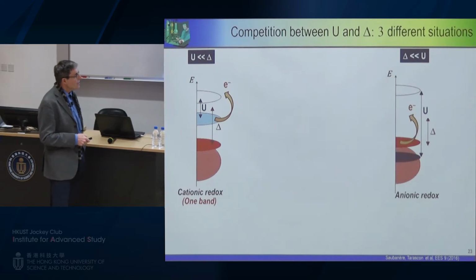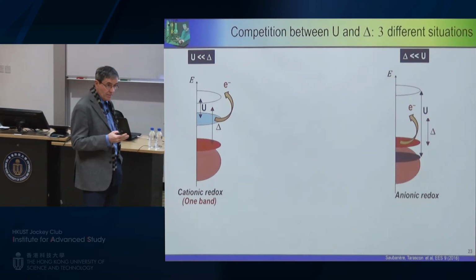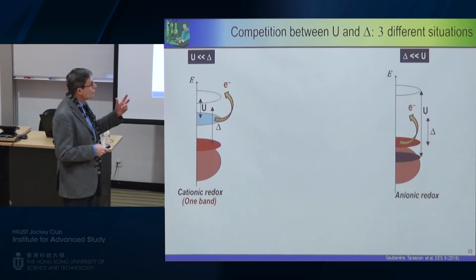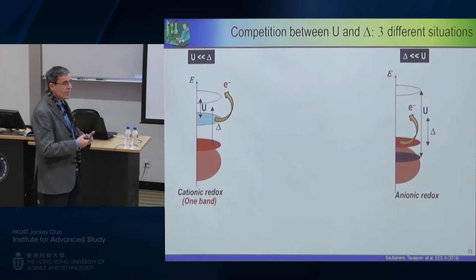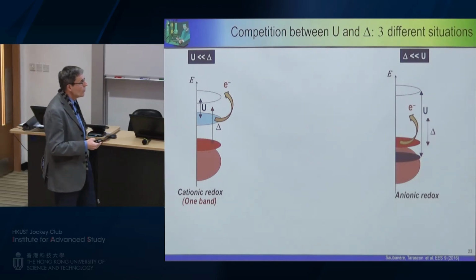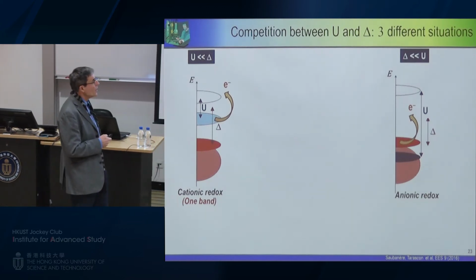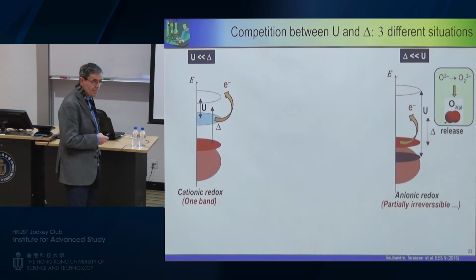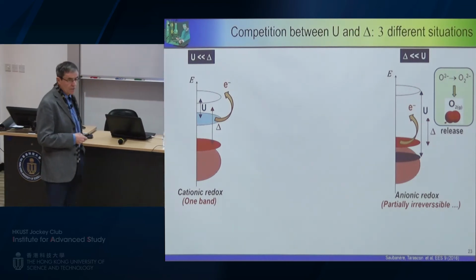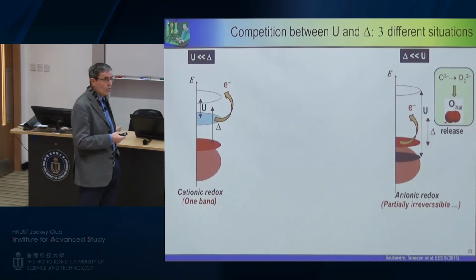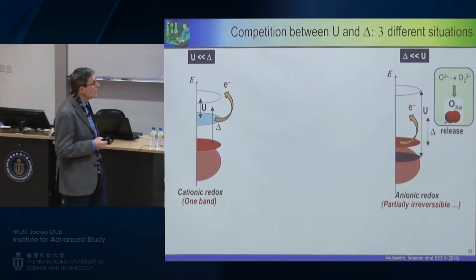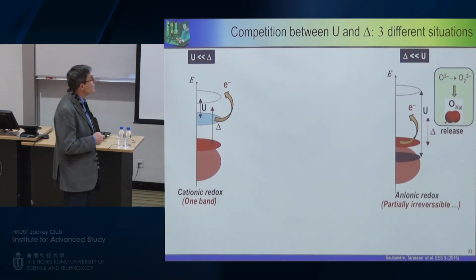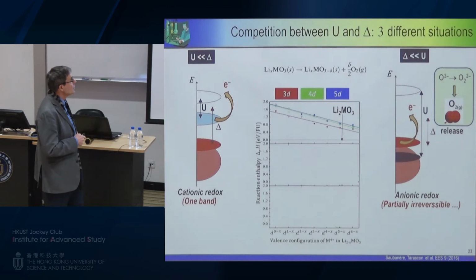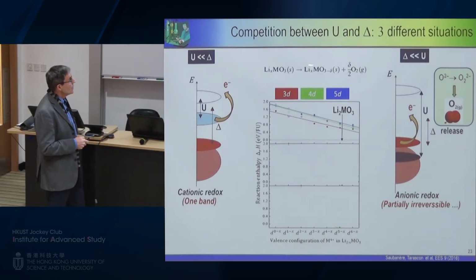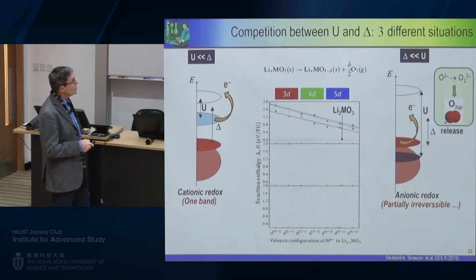And of course, in this case, since the chemical hardness of oxygen is very strong, automatically, when I am going to remove too many electrons, I create this kind of, I will say, peroxo-like species, which will be unstable, and the oxygen will try to be liberated from the lattice and to give oxygen gas. And this is what I will call a partial irreversibility. And we can figure out how the stability is going to change as a function of the d metal. And this was done by DFT calculation, where people have calculated the stability, the delta H associated to the reaction, which corresponds to the liberation of oxygen.